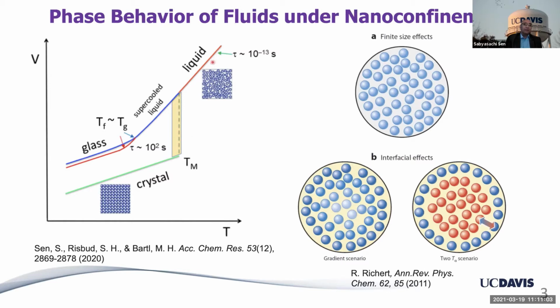All right, so the other option for the liquid to do is to change its volume continuously and go below the melting point. Because of kinetic reasons, it can bypass the thermodynamic transition. Atoms cannot move fast enough to arrange in an ordered lattice. And then this is called the supercooled liquid state, which is metastable below the melting point. And at some point, its viscosity increases so much that it basically becomes like a rigid solid, and we say it has undergone glass transition.